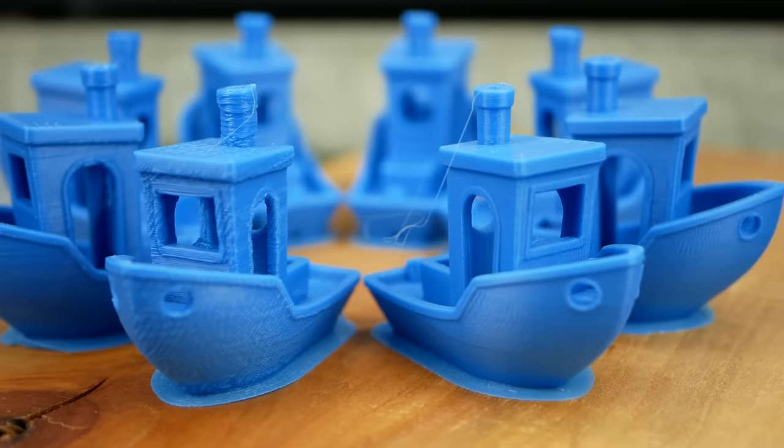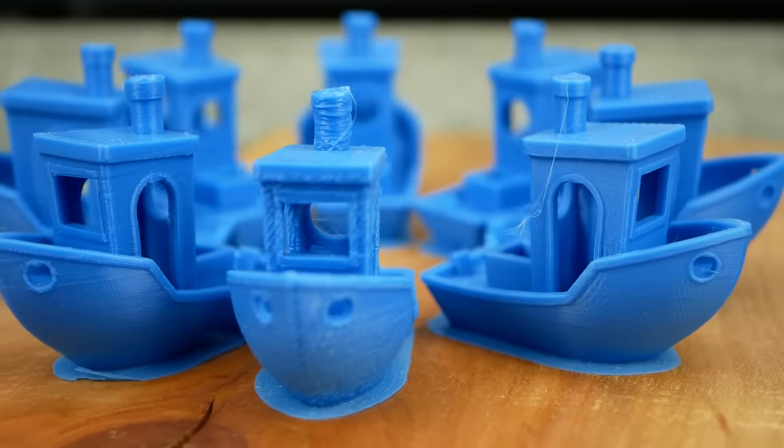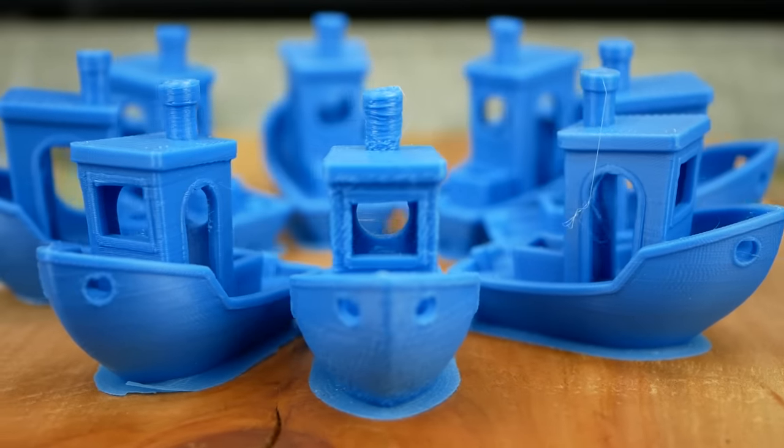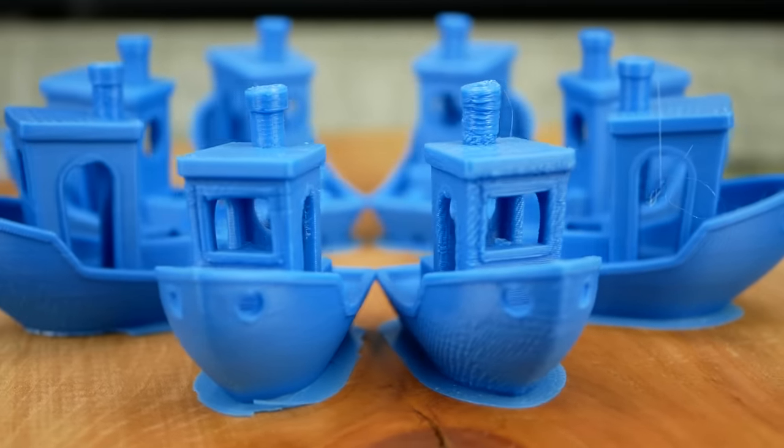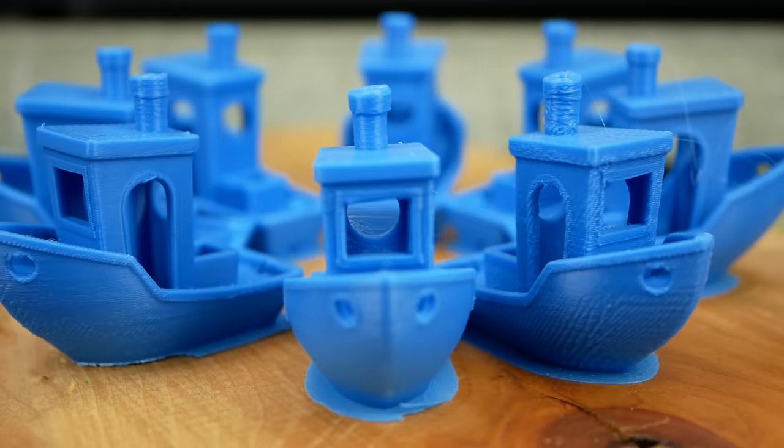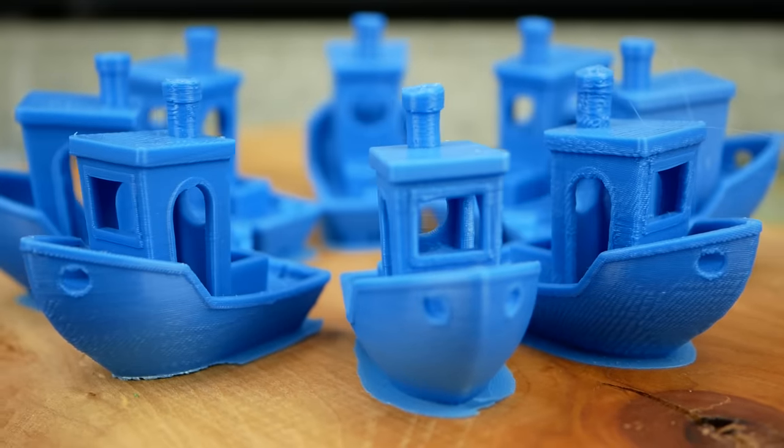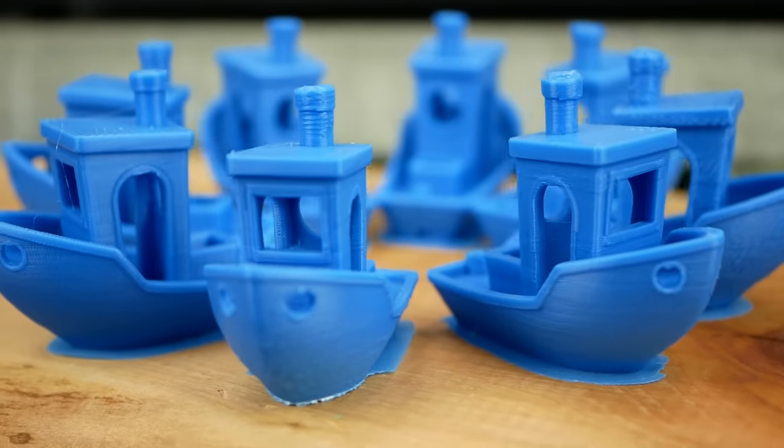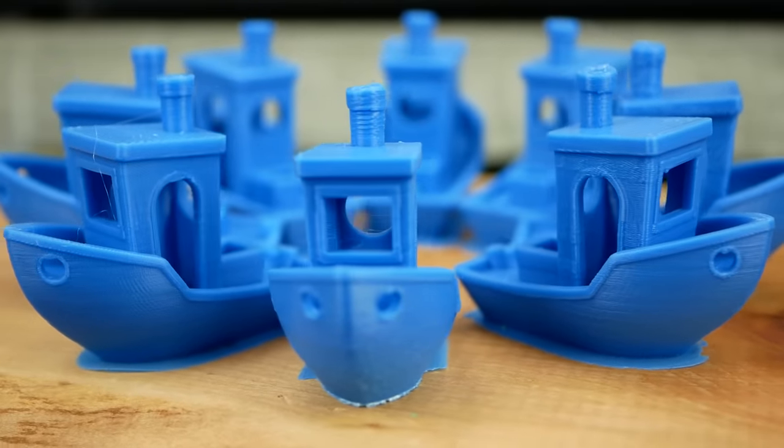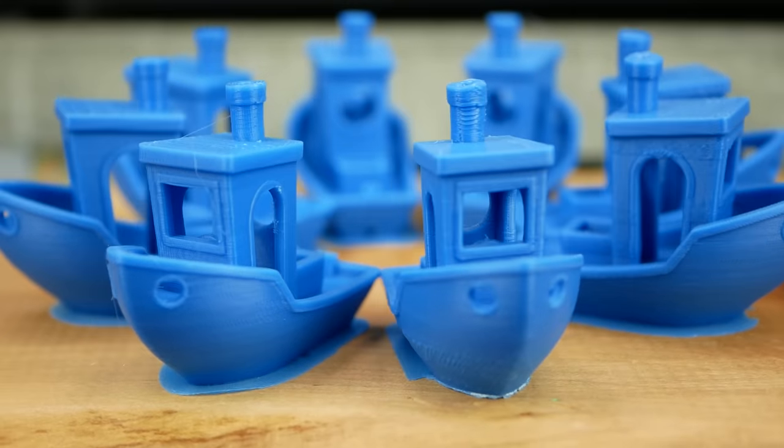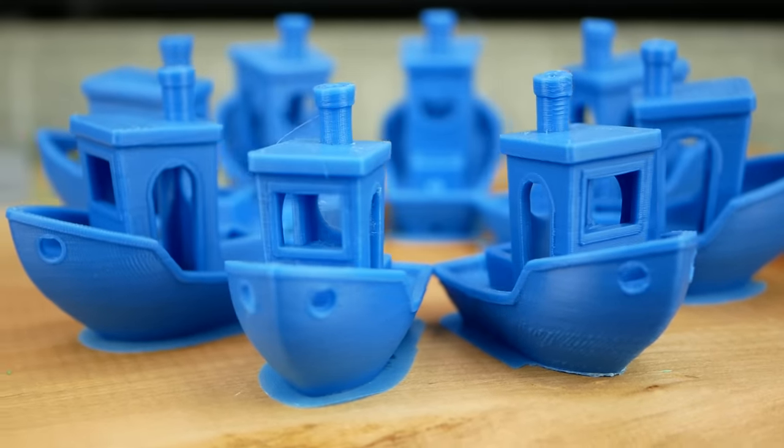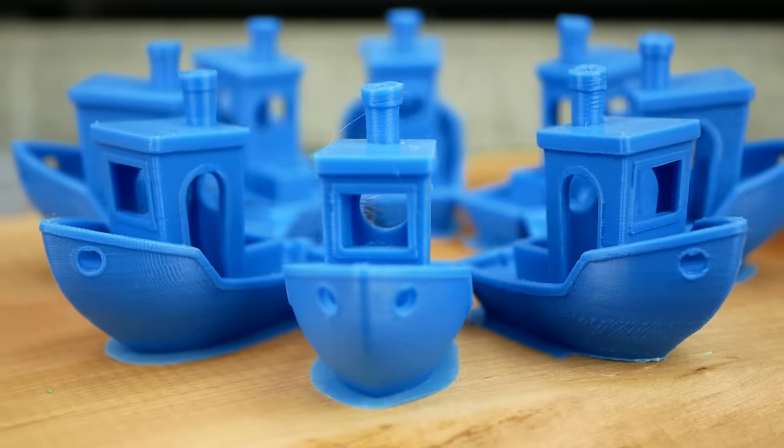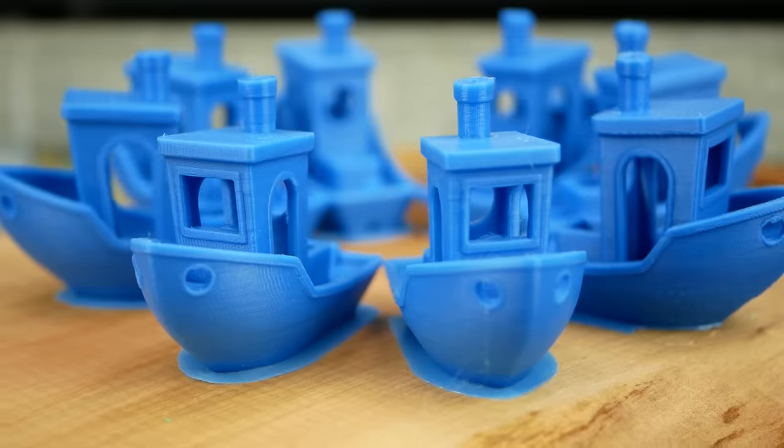All in all, the printable range is way bigger than I initially thought and 150% width still seems reasonable. You have to keep in mind that especially thin areas might suffer faster in quality because the additional extrusion pressure will create a downward force on the part, squishing it together.